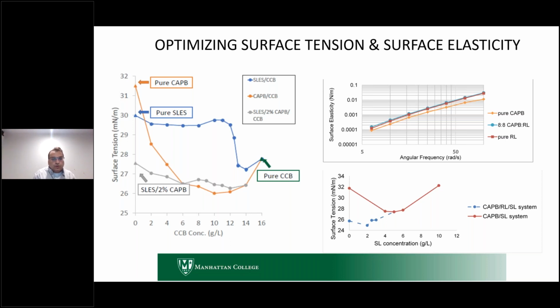which is actually lower than either the SLES Cap B system, and is definitely lower than the pure Cap B or pure SLES. But you get good properties when you combine SLES and Cap B. But what we've shown in this work is that we can even outperform that by introducing this CCB, this rhamnolipid, into the system, and get to an even better point in terms of optimization of the surface tension, or reduction of the surface tension.